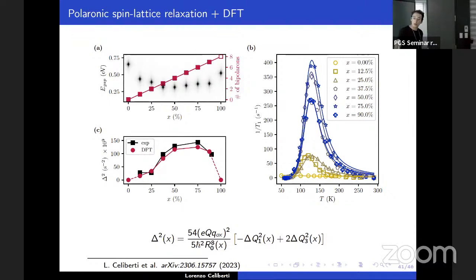And also got this very nice agreement where basically here only what we have is that these fluctuations are evaluated from the DFT calculation, as well as the average distance between osmium and oxygen. And we also have that basically the capital Q is the quadrupole moment of the sodium atom. This is taken from experiments, and Q_ox is equal to 2, the formal charge for oxygen ions in the derivation of this model.